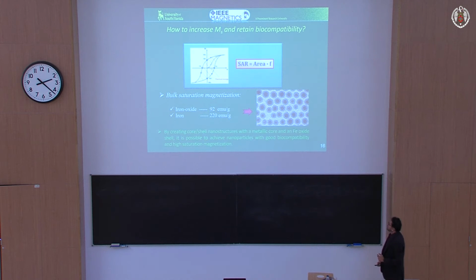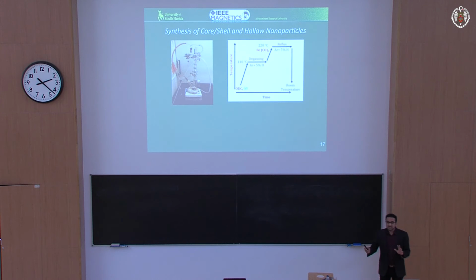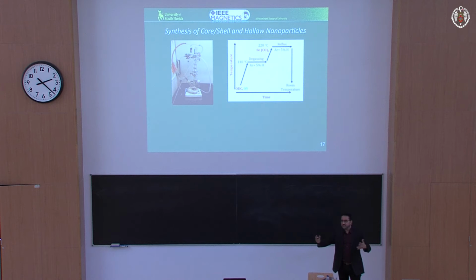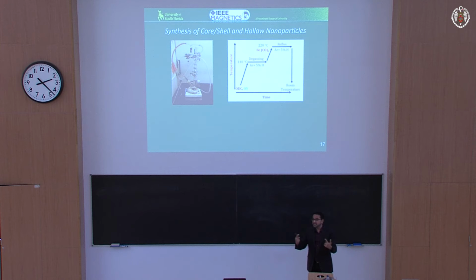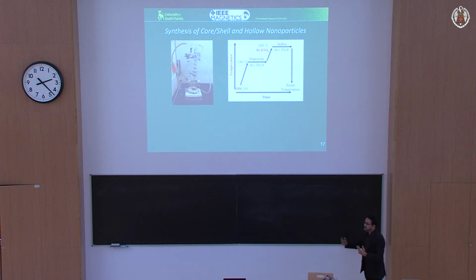For those of you that are interested in chemical synthesis, we use a very standard technique. This is thermal decomposition. It's nothing fancy. It's probably done in Madrid and other places here. Essentially, the idea is to control the particles and make monodispersed, high quality, single crystalline particles. The way you control that is by changing the reaction time, the temperature, and also the surfactants that you use during the growth process. You can, for example, change the surfactants and arrest the growth in different directions, and we can actually change the shapes of the particles using this technique. That's how we make these nanoparticles. So we started making this iron core, iron oxide shell particle.